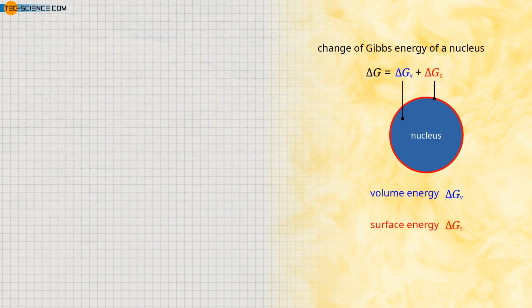To conclude this video, a note on the individual terms in the formula for the change in Gibbs energy. In it, we have attributed the change in Gibbs energy to the change in volume energy and the change in surface energy. In fact, deformation energy can also play a role in phase changes. While these can be neglected during the transition from the liquid to the solid state, they must be taken into account for phase transformations in the solid state. In the given equation, there is then a third positive term which takes these effects into account.